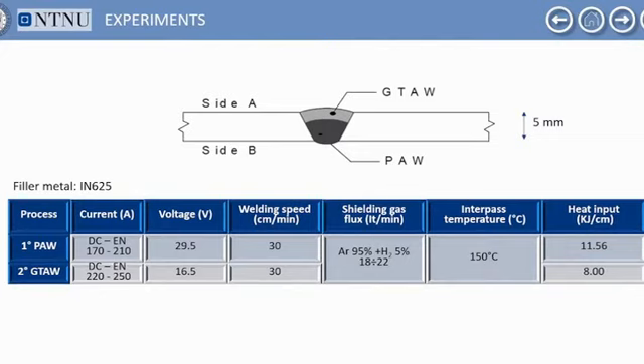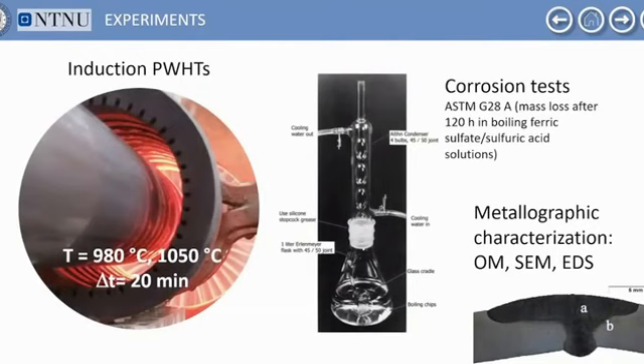This table collects the main important welding process parameter used in this experiment. After welding, we perform, of course, post-welding heat treatments using two different temperatures, 980 degrees and 1050 degrees, and we keep the holding time constant and equal to 20 minutes.